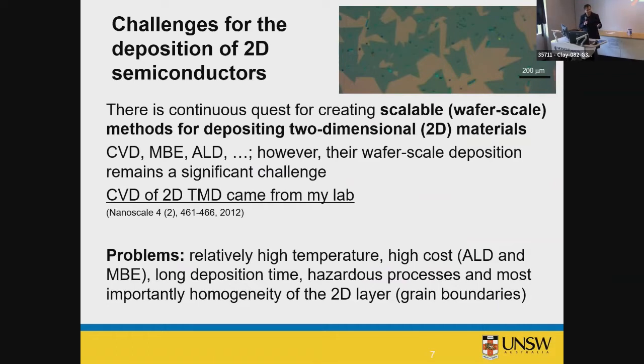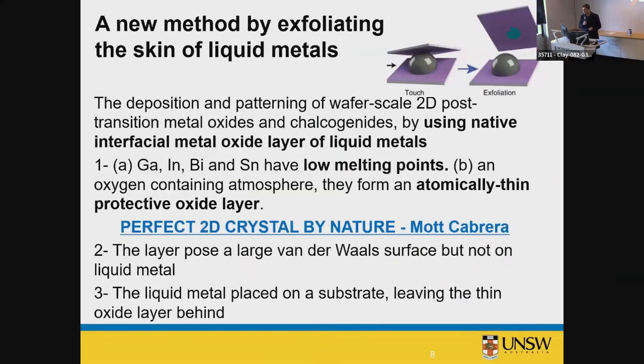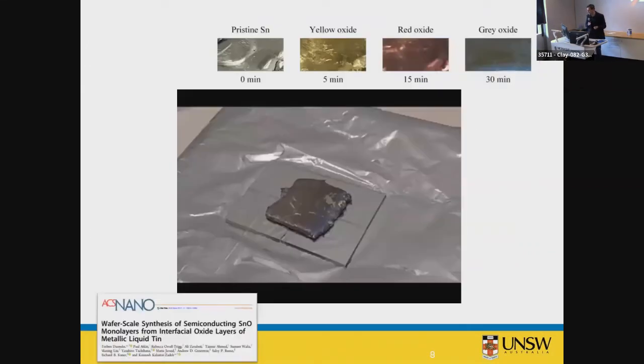MBE is extremely expensive. So we use what nature has given us, oxide or other two-dimensional materials on liquid metal. We just have to exfoliate them. It's on the surface of liquid metal. It's oxidized naturally based on Cabrera-Mott oxidation that happens. And if the surface of liquid metal is very large, you get single crystal as well. And you bring a substrate, stick the substrate to the liquid metal, and everything sticks to this substrate, so you can harvest it very easily. Here, the example.